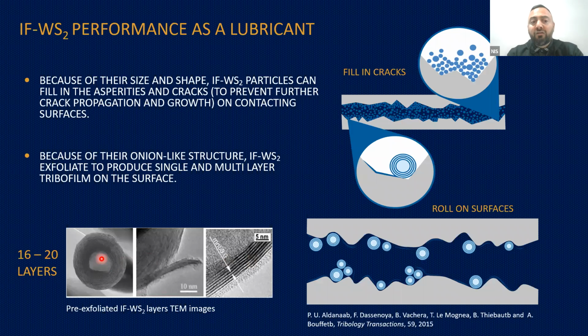benefits. Actual particles, when they exfoliate, you can see that there's a particle intact, with a hollow core and a multi-layer structure like an onion. And when you start damaging it, you produce these sheets, or tribofilm of tungsten disulfide. The very important point, which is sometimes counterintuitive to many users, is that unlike regular organic lubricants that do not contain solids, the more you damage the particles, the better the effect you're going to get. The more tribofilm you generate in the system, the better the effect you're going to get.